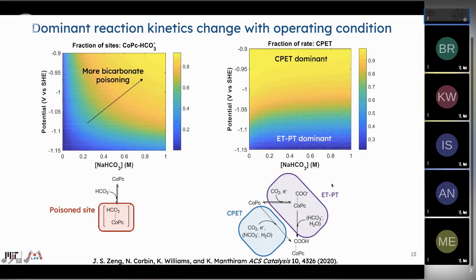What's very interesting here is that the dominant reaction kinetics change with operating condition. On the left-hand side, we've plotted out the fraction of sites that are blocked by bicarbonate. You'll see here that at more negative overpotential, so going to a larger overpotential, bicarbonate poisoning is disfavored. So one can electrostatically avoid it. And if you go to higher bicarbonate concentrations, bicarbonate poisoning is favored. And we can quantify this from the underlying model. We know the site balance at any given point in this wide phase space that we've tested.